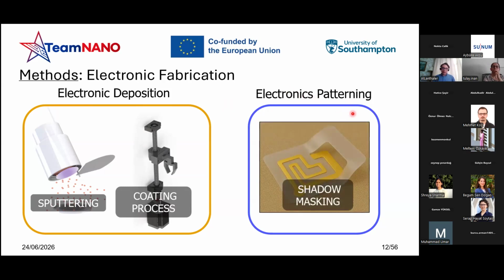Coming to the patterning, since I mentioned before, I wanted to get rid of the majority of the chemicals involved in the process, meaning that all the photoresists and etchants are not used in this work. I tried to focus mainly on the shadow masking effect, meaning that we are applying a mask on the very substrate we would like to fabricate on. And basically, you are depositing the thin film coating everywhere via sputtering, and then after removing the mask, as you can see, the desired layer stays on the textile itself.